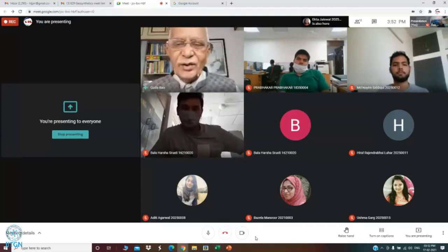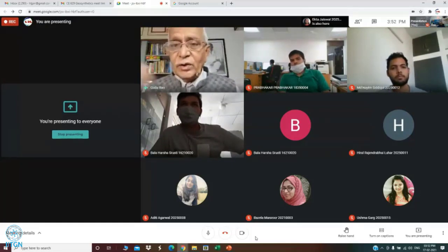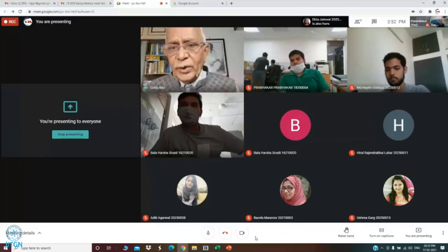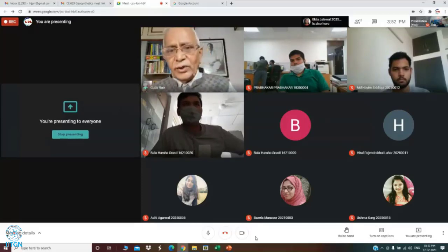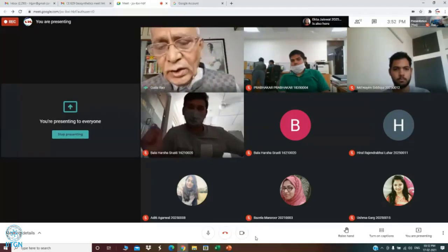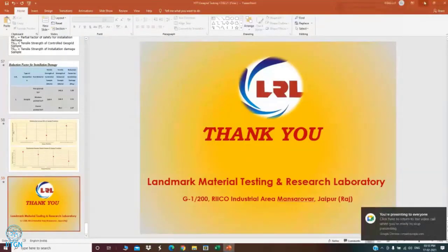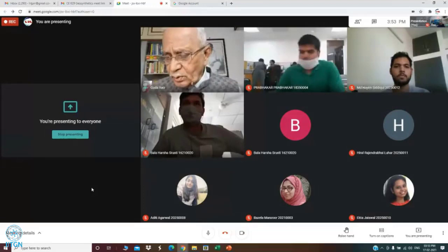So that also is a kind of cross check, where immediately we're able to see that value in front of us, because watching that testing, the testing is going to be very quick. The curve is going to fall, but it will still record the peak, and then of course it will keep going down. So one has to watch what is happening, and also whether the specimen is failing near the grips or not. Or whether all the ribs are trying to fail simultaneously or not. That is why we conduct a larger number of tests and sometimes visually record it, for consultancy and other purposes. We have to record the entire test. Video recording is easy now, and people can get something out of it. That is going to be most important for us to look into.